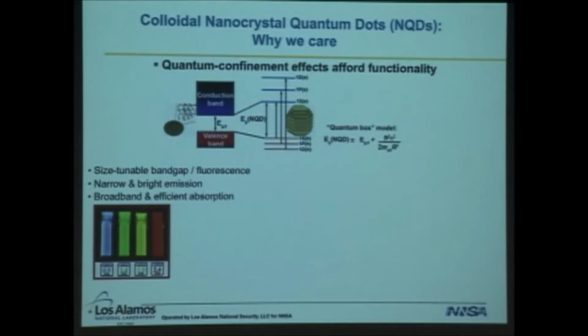And so simply by tuning the size, we can modify the band gap due to quantum confinement effects and therefore achieve fluorescence colors that span the entire visible spectrum. And the same idea can be applied to many other semiconductor systems, including other II-VI compounds, III-Vs, IV-VIs like the lead chalcogenides and so forth, and achieve similar tunability in other spectral windows.